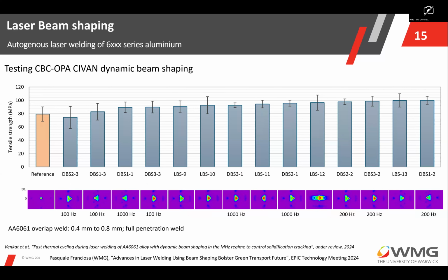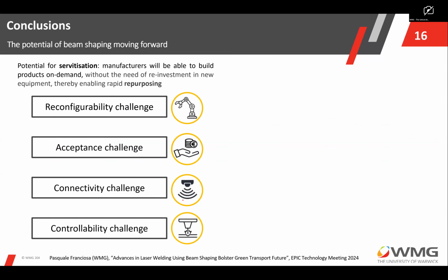So this only suggests one thing in the end, that changing the shape from a, let's say, round axisymmetric Gaussian or close to Gaussian profile to something else, like a triangular profile, has two main benefits. So first, the possibility of changing the thermal gradient, especially in the lateral direction. And by reducing the thermal gradient, eventually you are reducing thermal stresses, and because of the impact on the grain structure during solidification, there is a better chance that the welds will sustain the thermal load and wouldn't crack in the end. And the results are quite evident here.